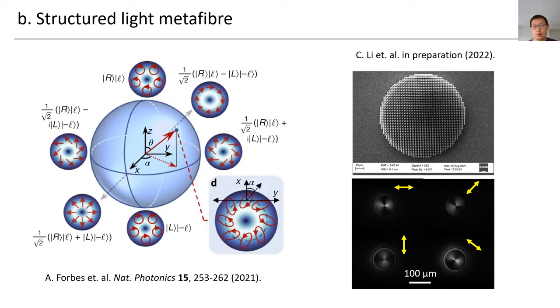Then we decided to put this structured light metasurface on top of a fiber to generate arbitrary structured light modes. Generation of structured light modes has been actively pursued for many years and has been achieved in free space using multiple specialized modulators, for instance. In general, you need two specialized modulators to control two different polarization components, either in the H-V linear polarization basis or the circular polarization basis, and you have to do a coherent superposition to synthesize arbitrary structured light. But using the metasurface, you can individually encode the polarization and the phase information, so you don't have to do this two-step superposition approach. You can just use a single metasurface to create an arbitrary structured light beam.